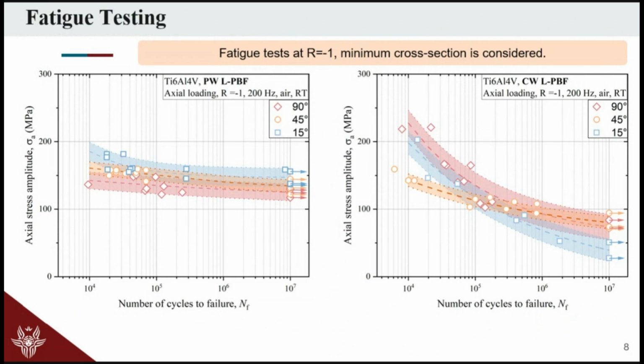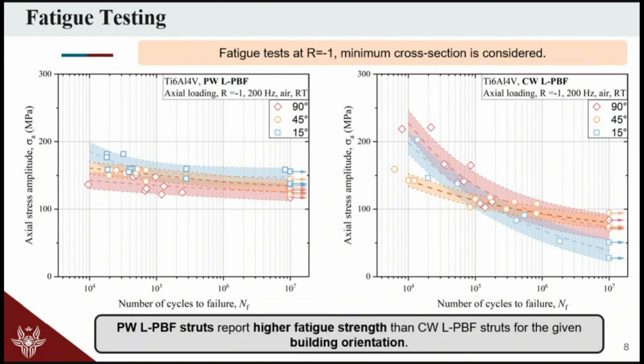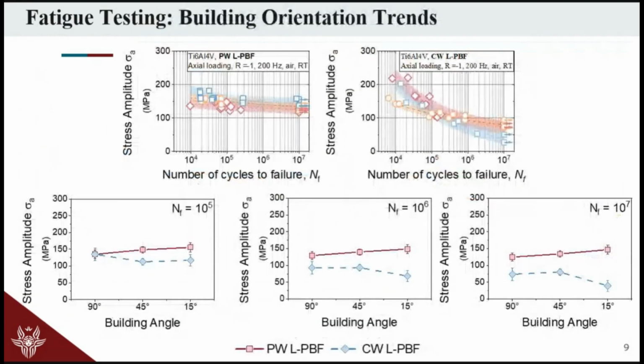So given this first look at these graphs, we can clearly say that the pulsed wave laser powder bed fusion reports higher fatigue strength with respect to the continuous wave laser powder bed fusion for any given building orientation. However, if we have a closer look at the different trends at fixed angles, at fixed cycles, at 10^5 numbers of cycles, 10^6 and 10^7, we can clearly see that these trends tend to increase with the increase of the numbers of cycles. And particularly for the 90 degrees, there is a perfect match at 10^5, which instead tends to decrease with the increasing of the numbers of cycles.